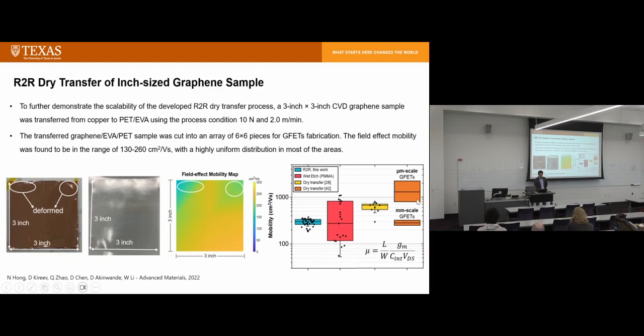Another study reported similar millimeter scale GFET results as our rotary roll samples. If you use small, micro scale samples, the channel size I showed you, our channel size, is 3 millimeter by 5 millimeter. If you make a channel size very, very small, like in a micrometer scale, you can get higher mobility. But it doesn't mean too much because you're looking at only one spot, whereas we're looking at the whole surface.